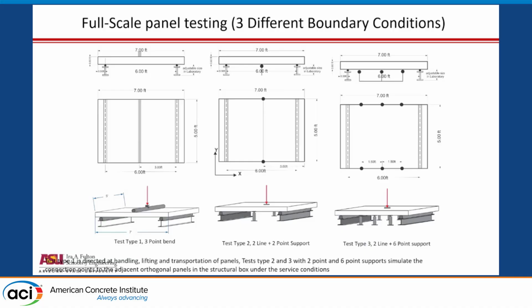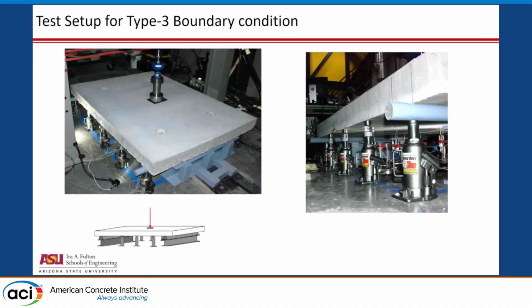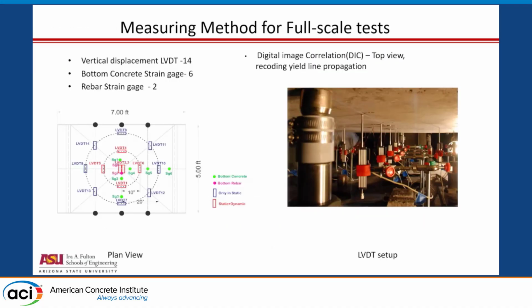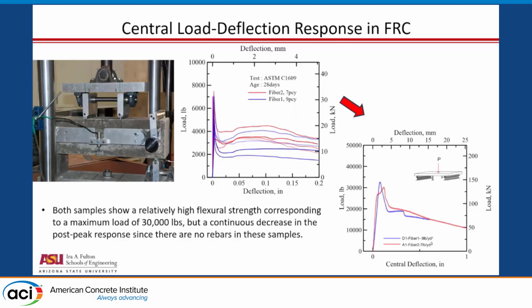And so 3 different sets of testing and a significant amount of instrumentation to be able to measure the crack patterns. Similar, different types of fibers, but these are all polymeric type fibers at this stage, because we wanted to reduce the potential for any kind of corrosion of the rebar. And then, of course, we tested full-scale sections and calculated the load and the residual value with different fibers.